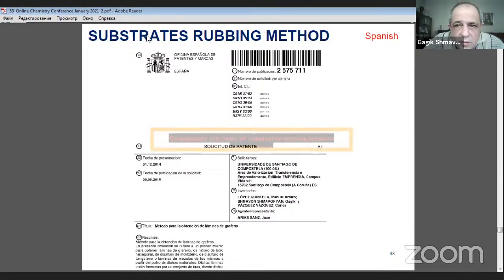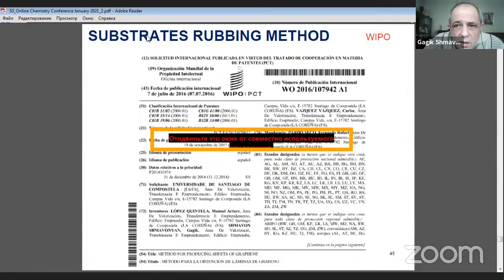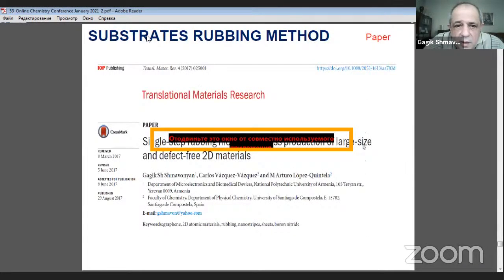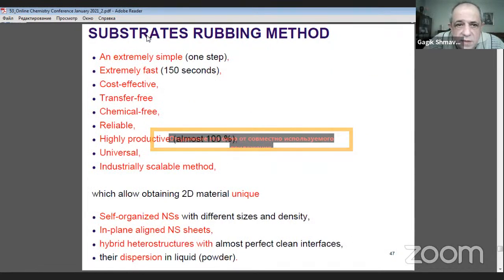This technology we patented. Here you can see the Spanish patent. Then we extended it to EPO and WIPO, and we also published our paper in the Institute of Physics journal Translational Materials Research. The substrate rubbing method is an extremely simple, extremely fast, cost-effective, transfer-free, chemical-free, reliable, highly productive, universal, industrially scalable method, which allows obtaining two-dimensional material with unique, self-organized nanostripes of different sizes and density, in-plane aligned nanostripe sheets, and hybrid heterostructures with almost perfect clean interfaces. They are available as dispersion in liquid or powder.